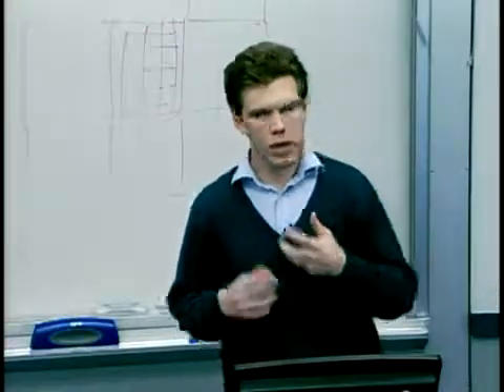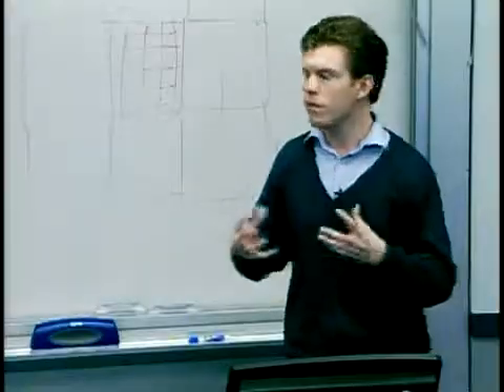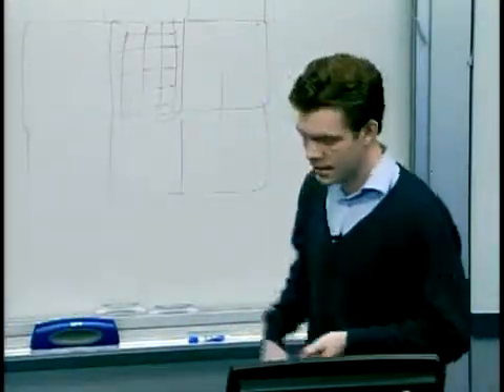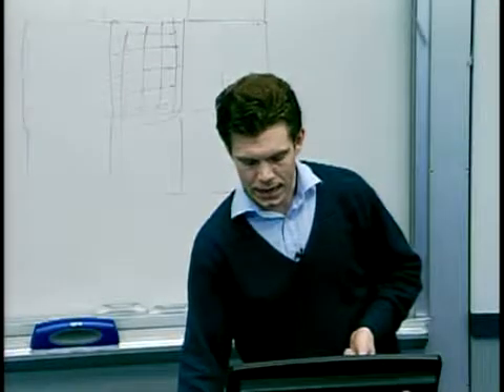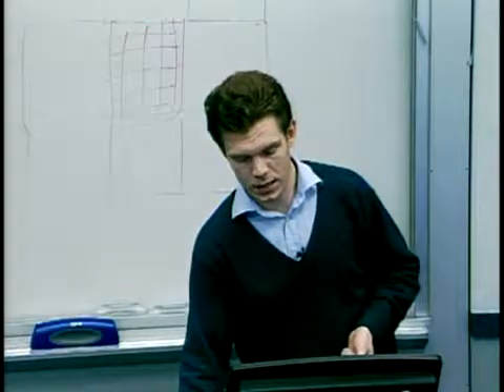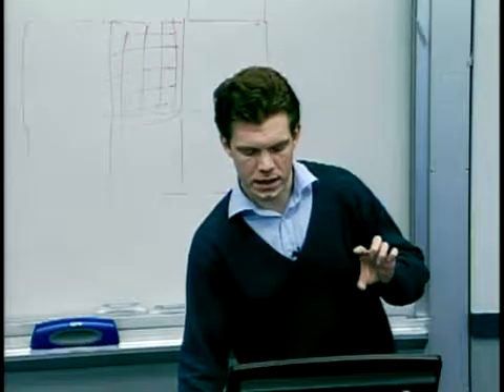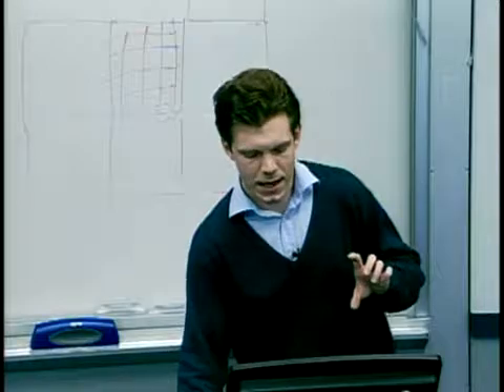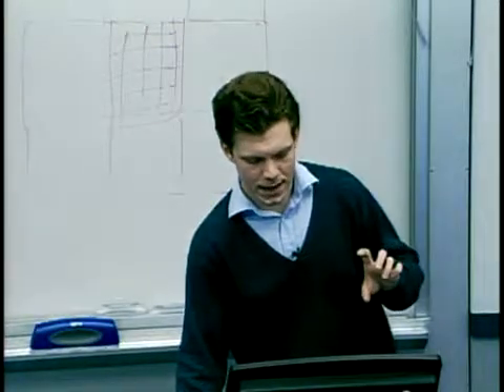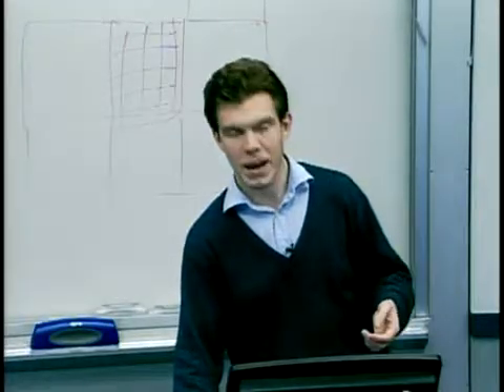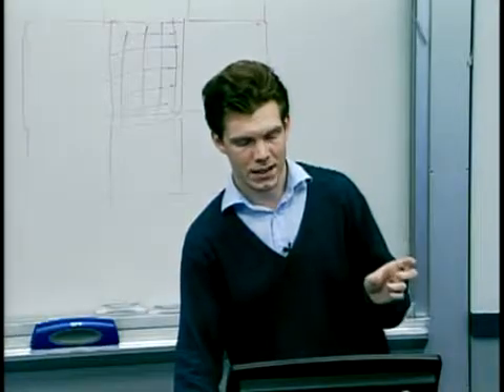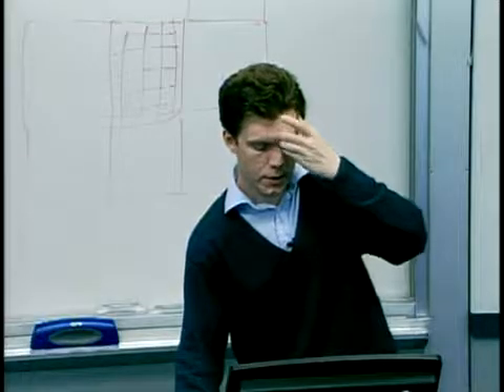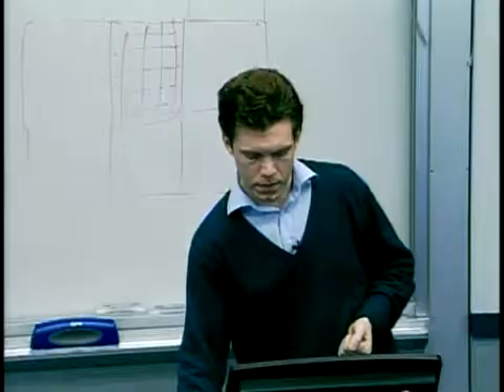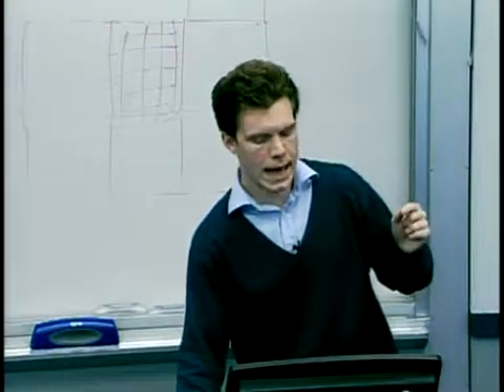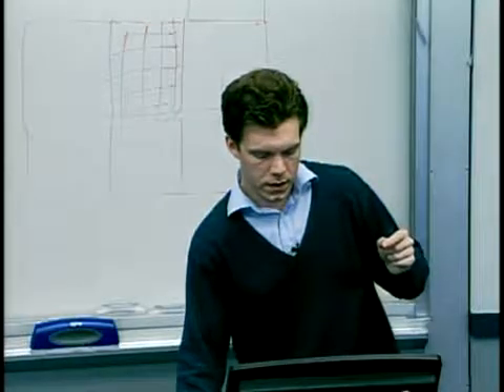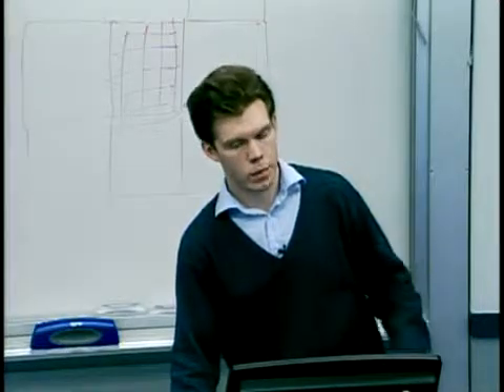So we can also abstract our experimental results and view them in simpler ways. One way of doing that is to look within each region of features and measure the peak penetration of material into the cavity. So we just measure the range of heights within the central 80% of the area of each patch of features, and then plot that peak penetration against some parameter. In this case, I've plotted the pattern density, which is the ratio of the cavity width to the cavity pitch. And the different colors in this graph represent different feature pitches, the pitch being the distance from one cavity to the next. And what I show is the elastic model matching up pretty well with the experimental results.